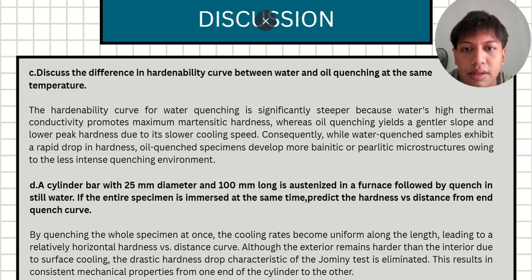For C, discuss the difference in hardenability curve between water and oil quenching at the same temperature. When comparing media, water quenching produces a significantly steeper curve due to its high thermal conductivity, promoting maximum hardness. In contrast, oil quenching results in a gentler slope and lower peak hardness because its lower cooling speed leads to bainitic or pearlitic microstructures.